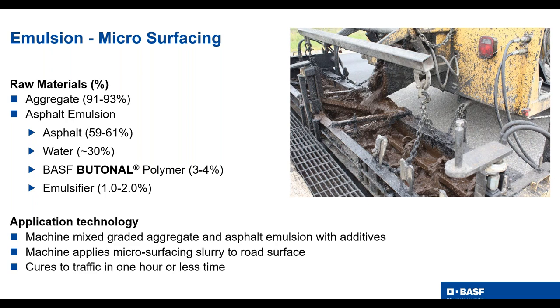This is a little higher polymer content than chip seals, but it's necessary due to the process in microsurfacing. The emulsifier loading is higher than what you'd see in chip seal as well, because of the specific type of emulsifiers that are used. They're very good emulsifiers that the suppliers have, and those are in the range of 1 to 2%. Usually you're looking at 1.2 to 1.4 as the average percentages.